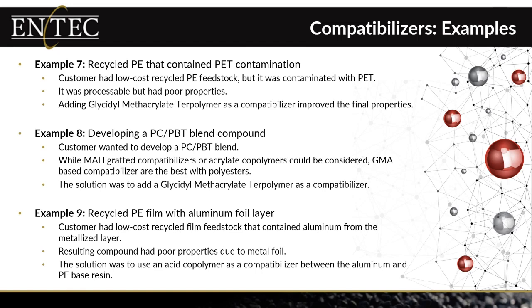The customer, again, had a low-cost feed stream, but had to deal with the PET. Again, as I mentioned, the glycidyl methacrylate compatibilizers work exceptionally well with polyesters. And in this case, that's what the customer ended up using to compatibilize those two products together so that they can make their final compound. Maybe you're developing a PC-PBT blend, and once again, you're going to take advantage of the properties of polycarbonate, the properties of the PBT, and combine them into a blended material. In this case, there's a number of products we could consider. Maleic anhydride grafted materials could work, acrylate copolymers could work, but because of that polyester component, GMA-based reactive compatibilizers will outperform the other materials.